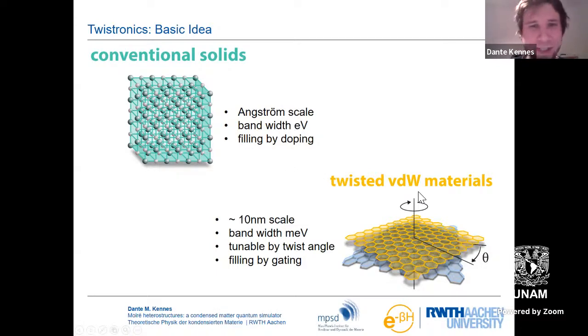But now, recently, this new arena emerged, which is illustrated here on the lower right, where you now use the twist angle to define a new length scale. We saw this in the previous animation. And when you go to small twist angle in these systems, for example, for twisting two layers of graphene on top of each other, you reach length scales which are around the 10 nanometer scale, so much larger than in these conventional solids. And that's by this geometric Moiré interference effect. And that in turn defines bandwidths which are much smaller. So these are typically around the 10 meV scale instead of the eV scale.